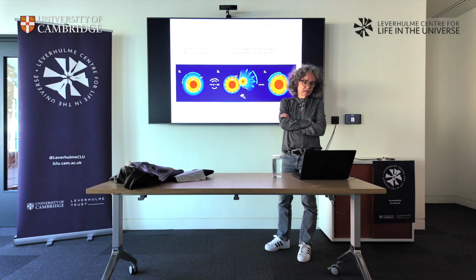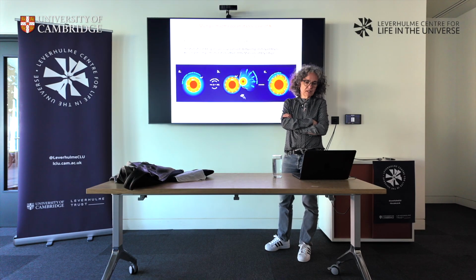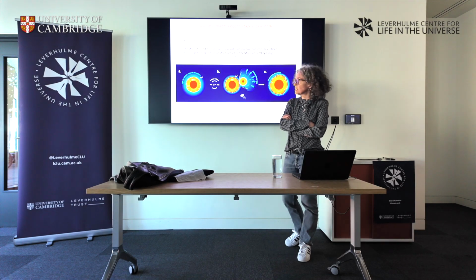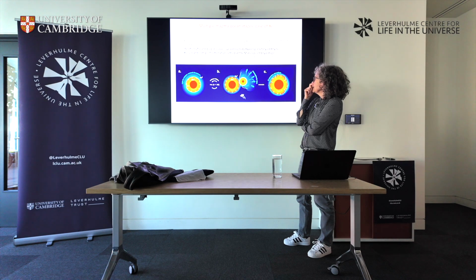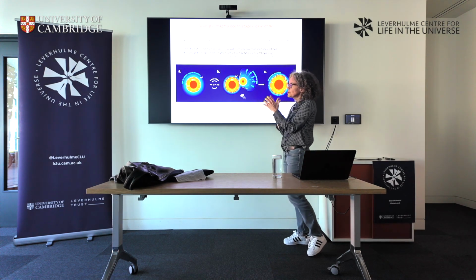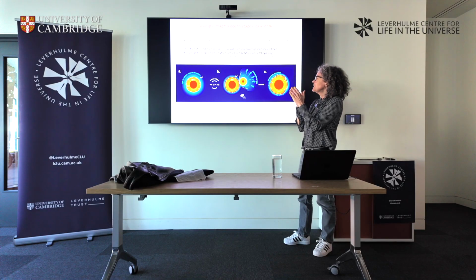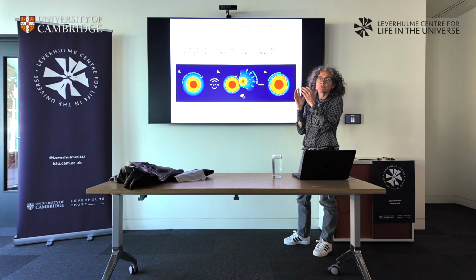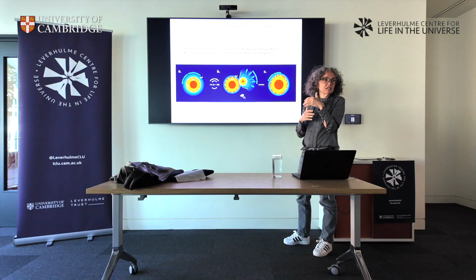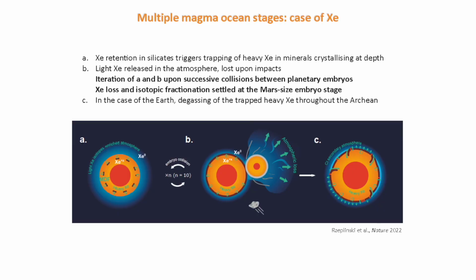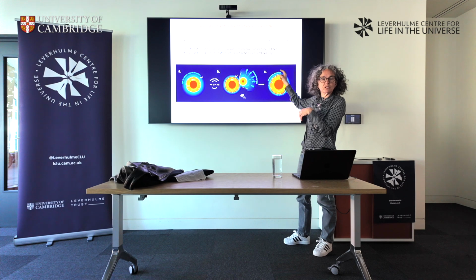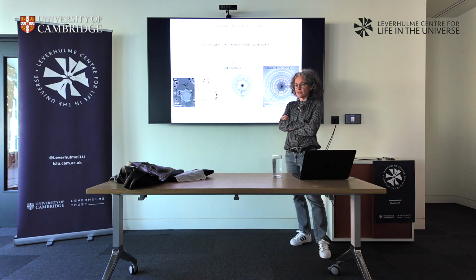So about 10,000 collisions between planetary embryos is actually consistent with modeling of planetary system formation. And in the case of the Earth, at some point, the system becomes closed. Because we have exactly the same xenon depletion in Earth and Mars, we think that the system becomes closed when the planet reaches Mars size. Somehow then it's heavy enough to retain its atmosphere, and the system becomes closed. So basically that's the story. And then subduction kicks in, and continental crust kicks in, and you probably have a release from the trapped xenon that makes the isotopic evolution of the atmosphere that is recorded. That's the Earth science side of the story.